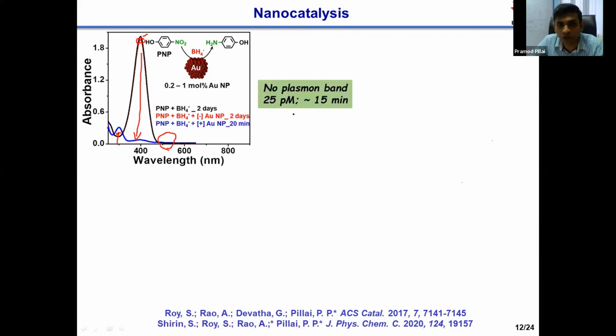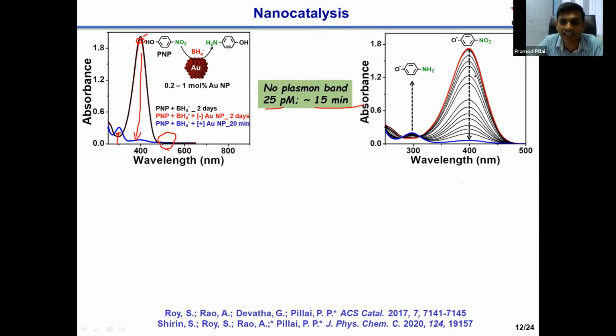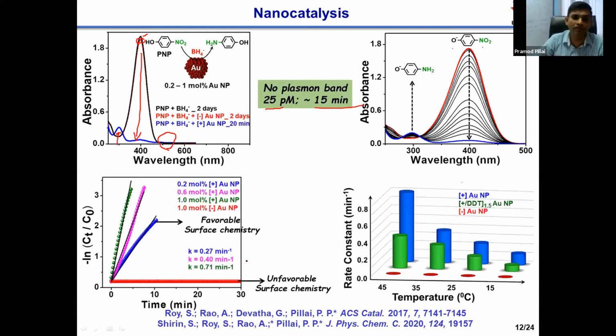In fact, we have calculated that we are able to do this catalysis with 25 picomolar of catalyst within 15 minutes. So this is the impact of surface chemistry. By appropriate surface chemistry, you can reduce the amount of catalyst that is required, and you can control the catalytic performance. So once we got the initial result, we did the detailed kinetic studies by monitoring the change in the absorption of the reactant, and we came up with a pseudo first order kinetics.